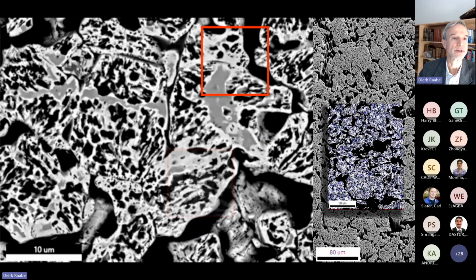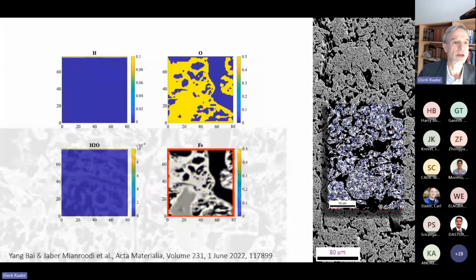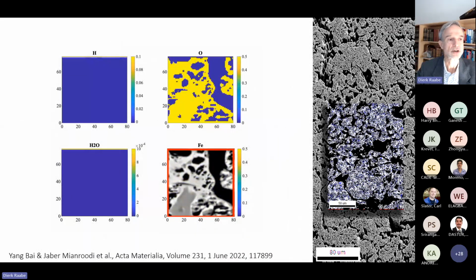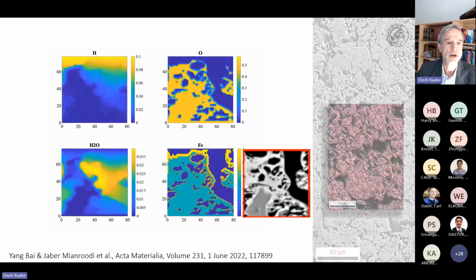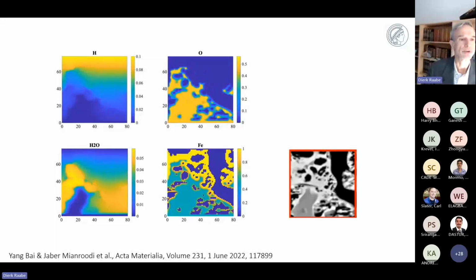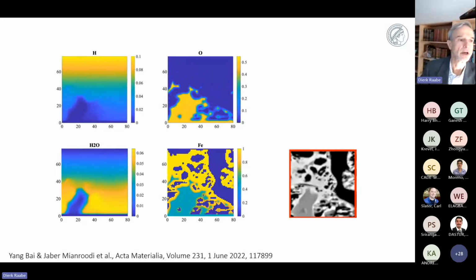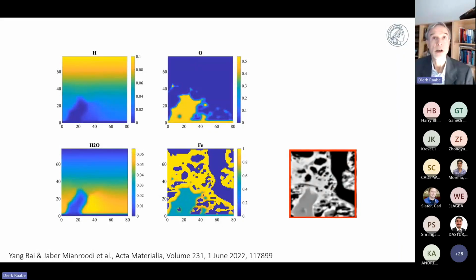We try to put this into a phase field simulation that you can see here. That means we take such patches and solve the transport and the Cahn-Hilliard and the Allen-Cahn equations for these phase transformations. I cut that here a little bit short. When you want to go deeper into the phase field simulation, I would be happy to discuss that with you after the presentation. But the point is that you can essentially, by fitting the iron oxide, so the wüstite to iron transition in a corresponding Landau functional form, and solve the Cahn-Hilliard and Allen-Cahn equations.